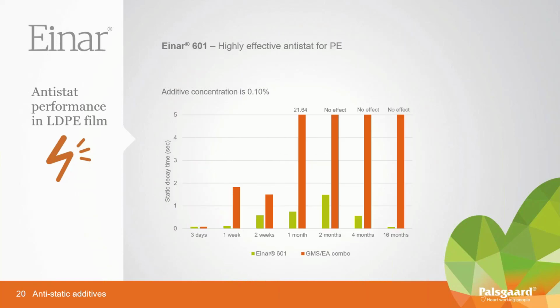On this slide, we're showing results for our Einar 601 in polyethylene film. Einar 601 is a highly efficient anti-stat that will work really well at low loading levels in many different polyethylene film applications. And here we're showing again that ethoxylated amine anti-stats can be replaced efficiently by chemistry that is glycerol ester based and generally regarded as a chemistry with high, unquestionable safety, as it's also used as additives directly added to food.